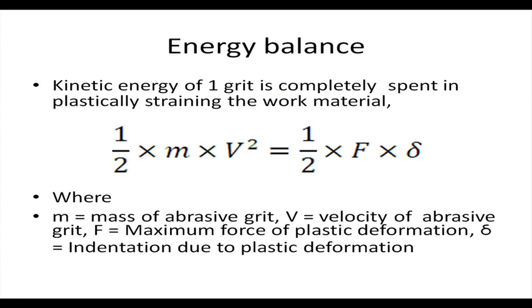What we see is that a grit is coming and hitting the workpiece surface, and the grit is, mind you, at very high speeds. So, when it hits the workpiece surface, how does the material get removed? Here we assume that the complete kinetic energy of the grit is converted into plastic strain energy of the work material. So, if the work material is plastically deformed, the work done due to this plastic straining can be expressed as half into F into delta, where F is the maximum force of plastic deformation which is occurring, and delta is the indentation due to plastic deformation.